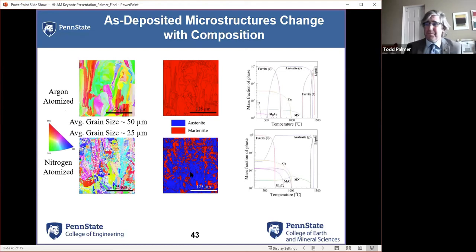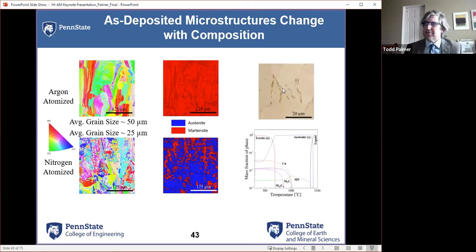Now, a little trick here. The austenite here, this retained austenite, will transform to martensite when you polish it. So in order to obtain these nice, pretty pictures with our EBSD, we had to ion mill the surfaces. We went through the polishing, went to a colloidal silica suspension, and then when we would try to look at the EBSD with that, we would find that everything was martensite. XRD had told us before that it was austenite. So we actually had to revise our sample preparation procedures in order to see this. And that is a little bit of that delta ferrite in this microstructure, so we have evidence that it's there.